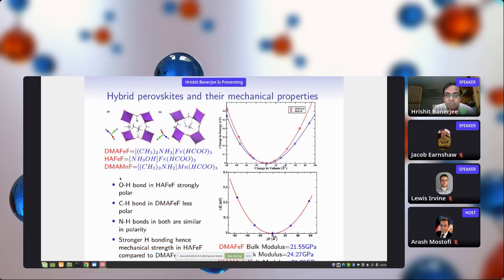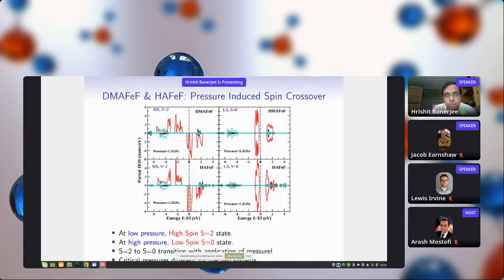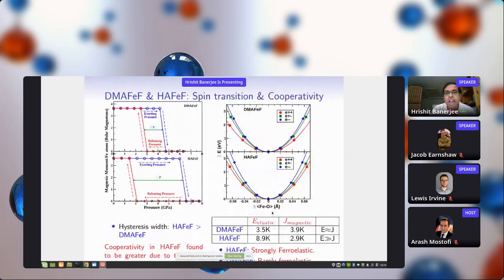Well, we take three different examples: dimethyl ammonium iron formate, hydroxyl ammonium iron formate, and dimethyl ammonium manganese formate. And with these, we study the systems. We show that for both dimethyl ammonium iron formate and hydroxyl ammonium iron formate, a pressure-induced spin crossover is possible, and their critical pressures are very different. And we also show that when we release the pressure, we get hysteresis of different widths in these two materials.